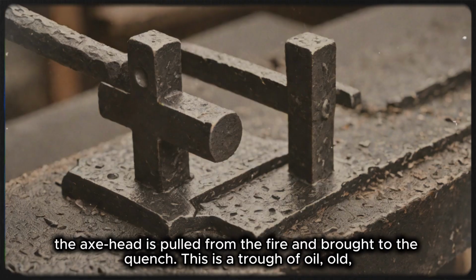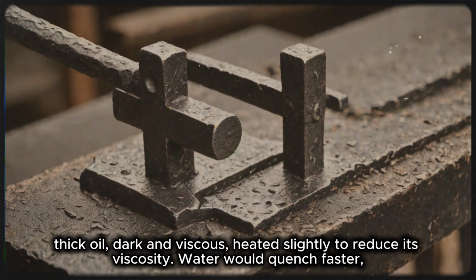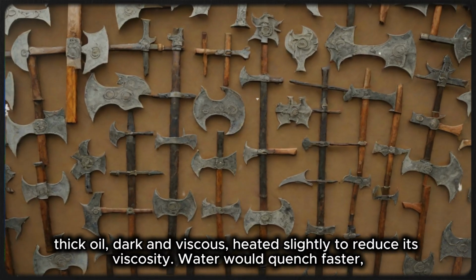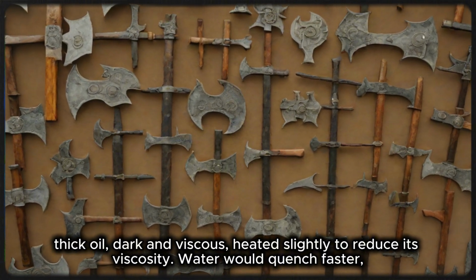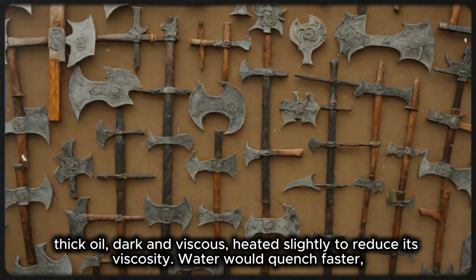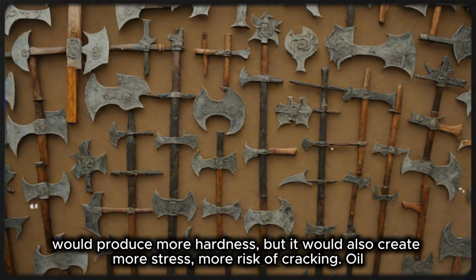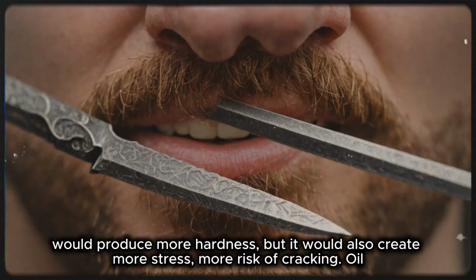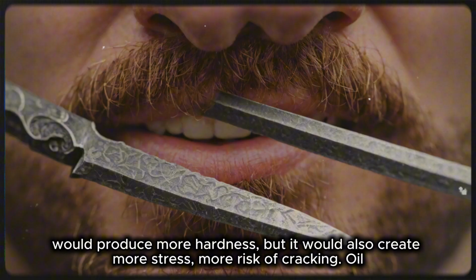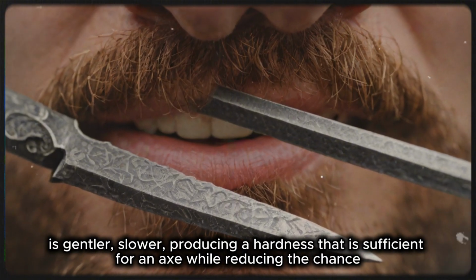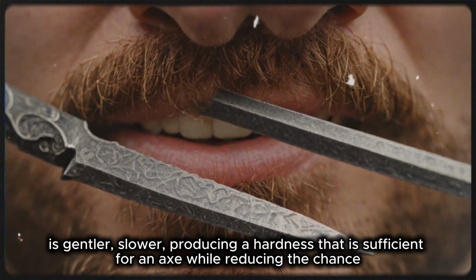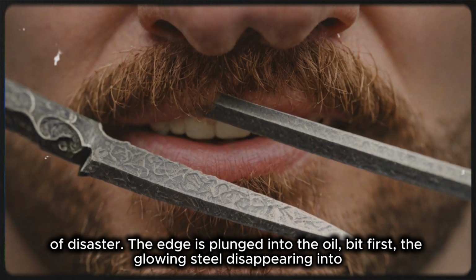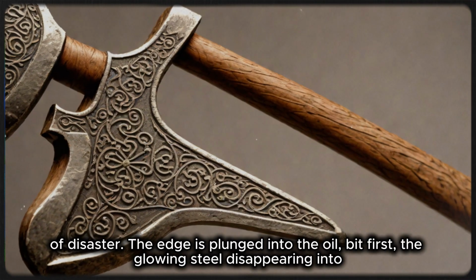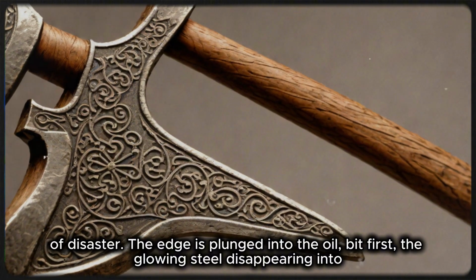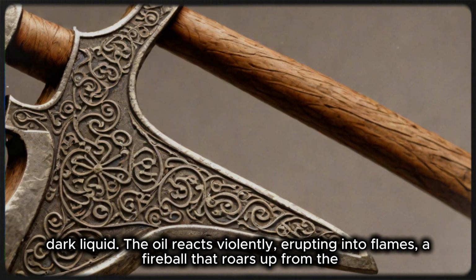When the color is right, the axe head is pulled from the fire and brought to the quench. This is a trough of oil, old, thick oil, dark and viscous, heated slightly to reduce its viscosity. Water would quench faster, would produce more hardness, but it would also create more stress, more risk of cracking. Oil is gentler, slower, producing a hardness that is sufficient for an axe while reducing the chance of disaster. The edge is plunged into the oil, bit first, the glowing steel disappearing into the dark liquid.